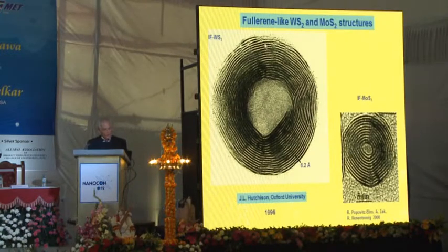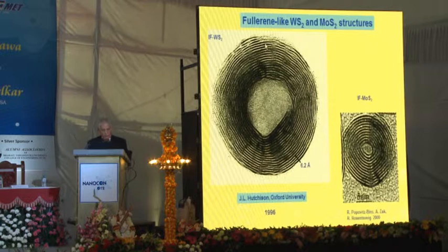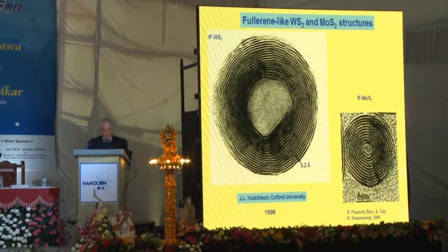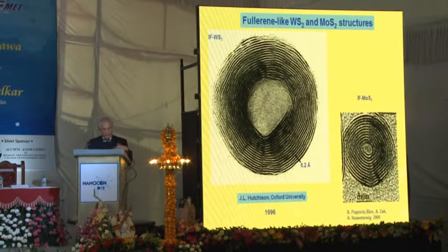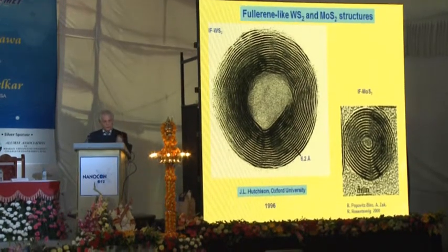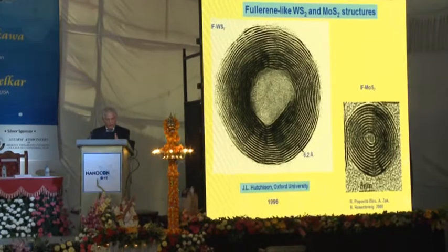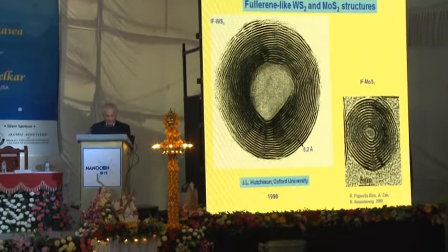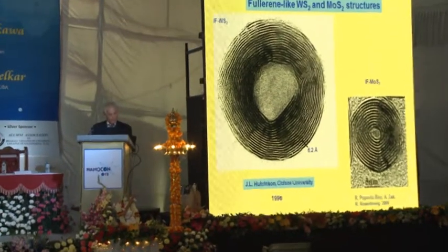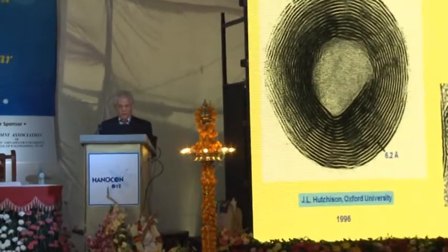Each black layer is a tungsten disulfide layer, which is folded one into the other in about 15 subsequent layers. And if you compare it to C60, which is made of precisely 60 atoms of carbon, this is nothing similar because it is much larger. There are about 300,000 atoms of molybdenum and tungsten in this structure. And there are many defects here, but nonetheless, it's a hollow closed structure.